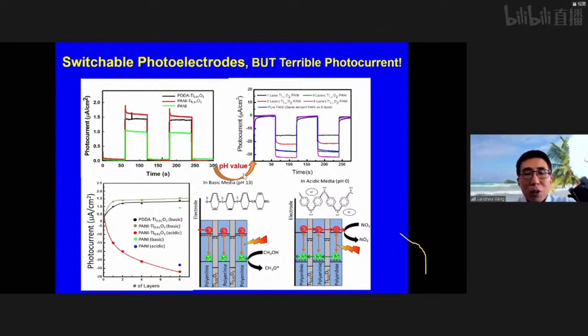Of course, we found some other interesting phenomena, like the switchable photocurrent. But in terms of the scale, the photocurrent density is basically a microampere per square centimeter. This is barely about 1% of the theoretical photocurrent of TiO2. So then we have been thinking about why TiO2 material can only achieve this small photocurrent. Basically, two things. The first thing is that the charge transfer pathway on this layer-by-layer assembled nanosheet is not that good, because in between there are some polymers that possibly block the charge carrier pathway. The second one is that the film is very thin, and it's not able to absorb too much light.